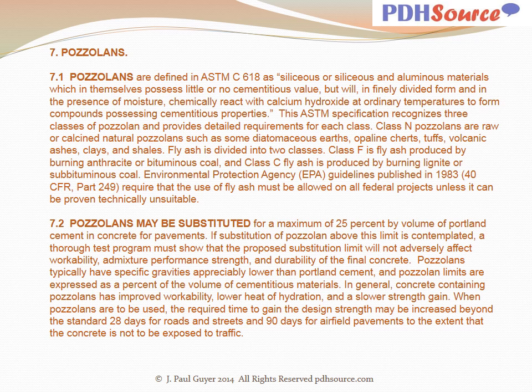Pozzolans may be substituted for a maximum of 25% by volume of Portland cement in concrete for pavements. If substitution of pozzolan above this limit is contemplated, a thorough test program must show that the proposed substitution limit will not adversely affect workability, admixture performance, strength, and durability of the final concrete. Pozzolans typically have specific gravities appreciably lower than Portland cement, and pozzolan limits are expressed as a percent of the volume of cementitious materials. In general, concrete containing pozzolans has improved workability, lower heat of hydration, and a slower strength gain. When pozzolans are to be used, the required time to gain the design strength may be increased beyond the standard 28 days for roads and streets and 90 days for runways and taxiways at airports and airfields.